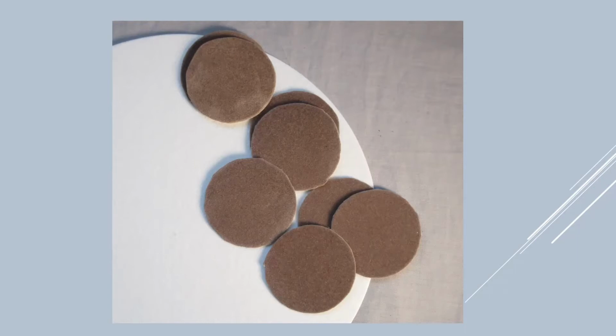The one that looks like it's sitting on a dinner plate is a cloth that is flat, and it gives us better in situ replicas. But we use the cloth with the fuzz, the fur on it, because if you're in an environment like a fired heater or a boiler where there's some refractory dust, or in the case I was working in a farmer's field on a pipeline, and he was plowing his field, you want something where all those dust particles can hide in all of this fiber and not scratch your surface.